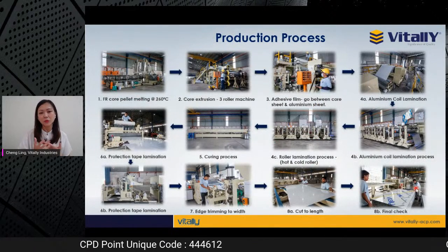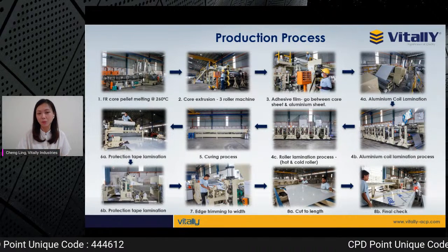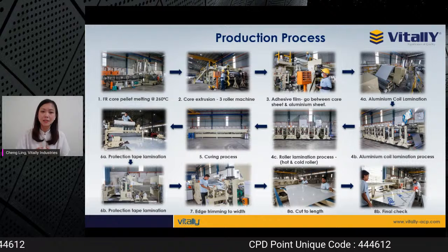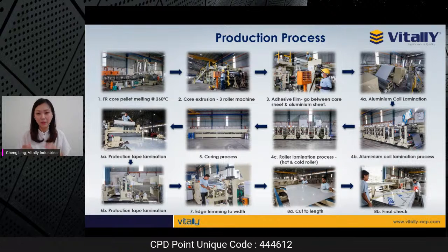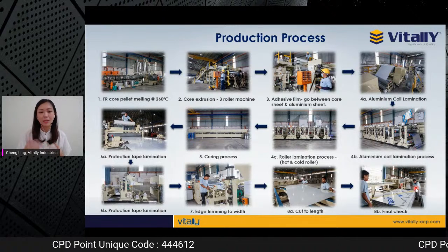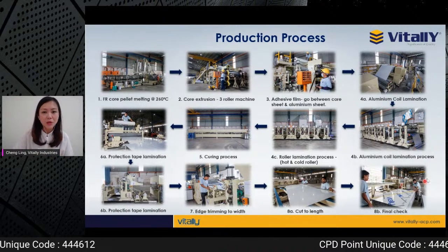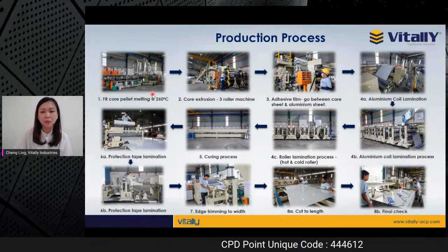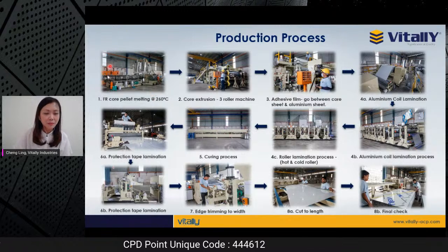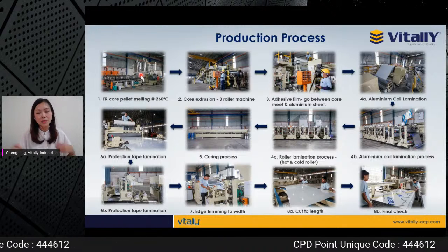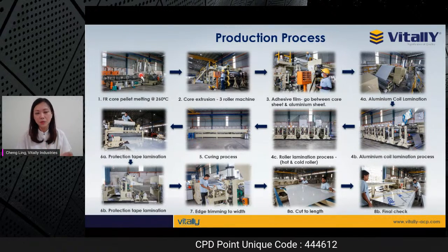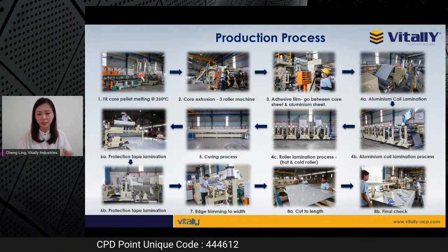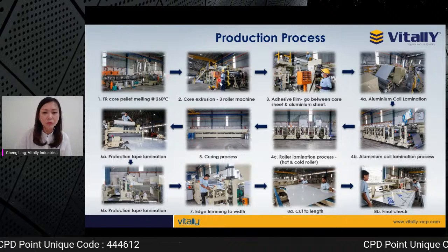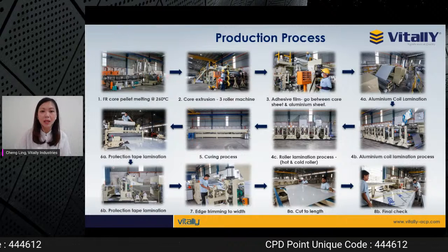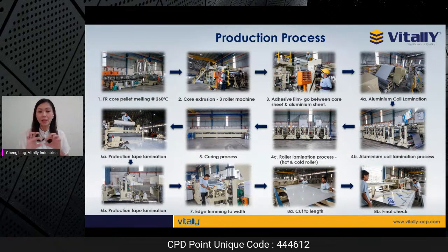Okay, some of you may wonder how we actually produce our panel in our factory, right? We have our own laminating line in our factory, and we do the lamination process locally. I'll briefly explain the step-by-step production process. The first step is the melting process for the core material. When the core material comes in, it's in pellet form, so we have to melt it using our boiler machine. After melting, it goes through our 3-roller machine, and then it comes out in a flat shape for the coil itself, right?